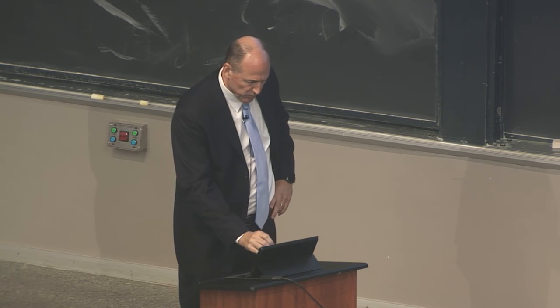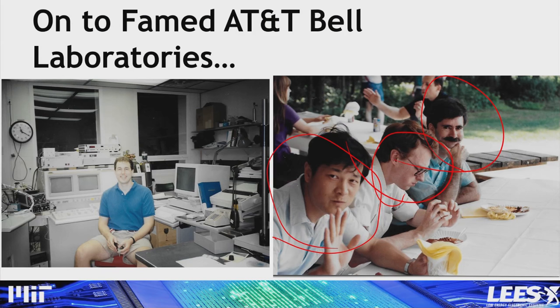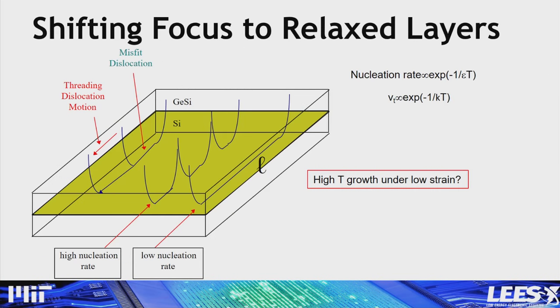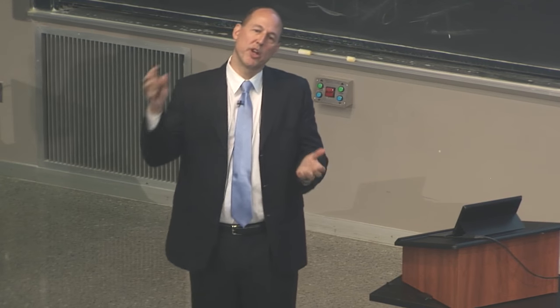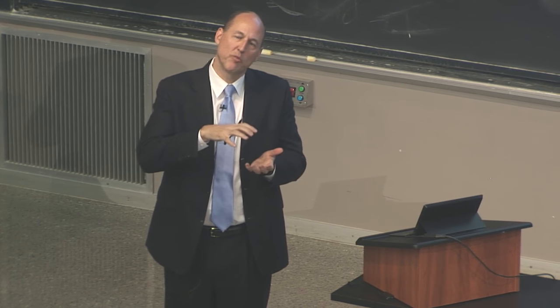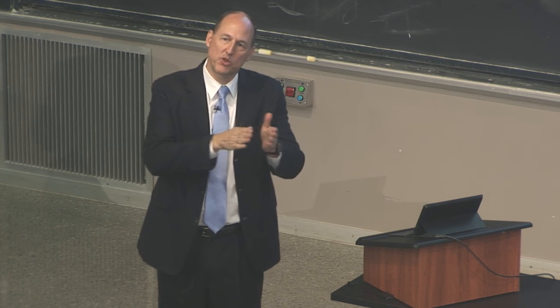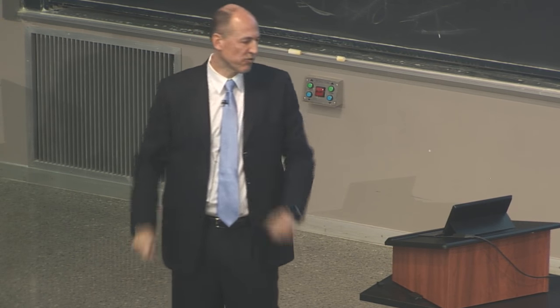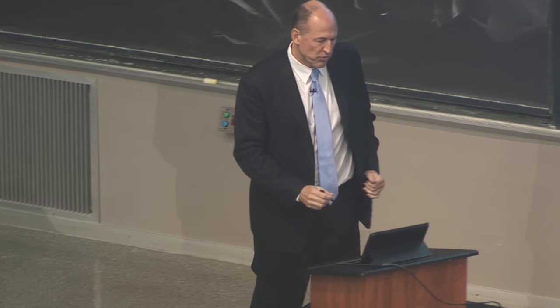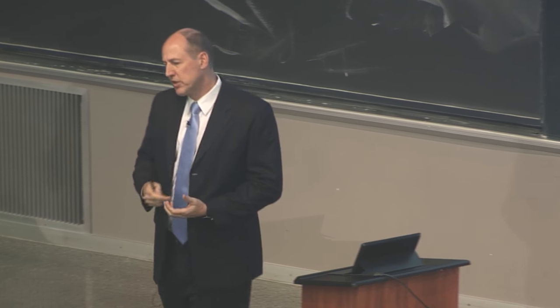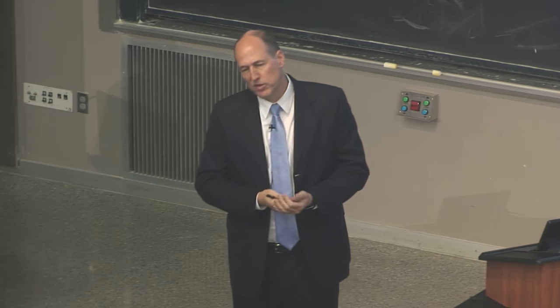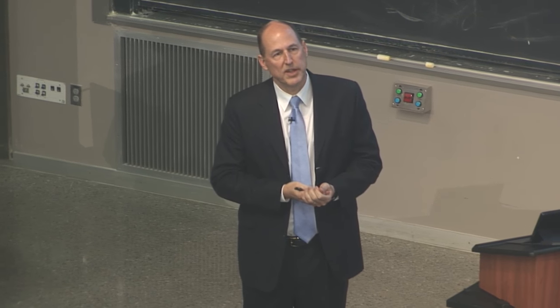And Connor Rafferty ended up doing a startup later on germanium detector arrays on silicon here in the Boston area. So the shift here was now trying to do not the strained layer, but to put relaxed layers on top of this substrate and make it completely relaxed so we could shift the lattice constant and build new kinds of devices. And what I'm trying to show you here is that a lot of times the things you learn in the university, it's the empirical relationships that you need to get started.